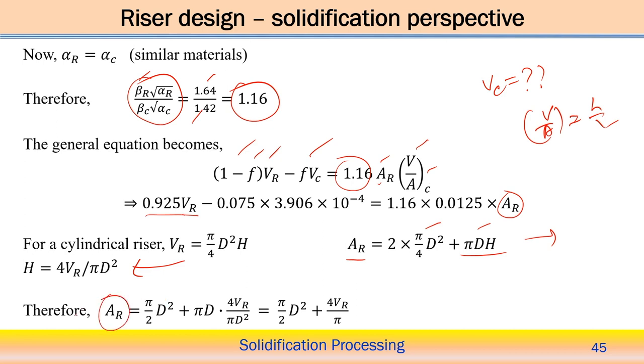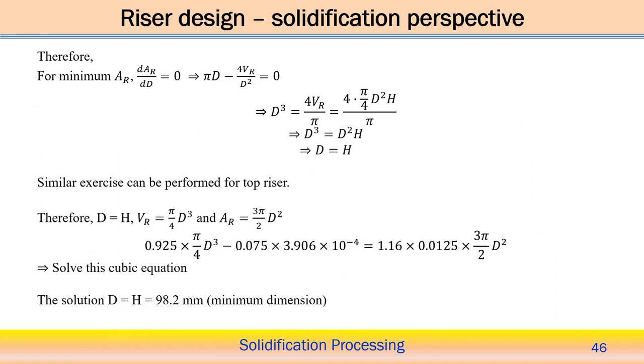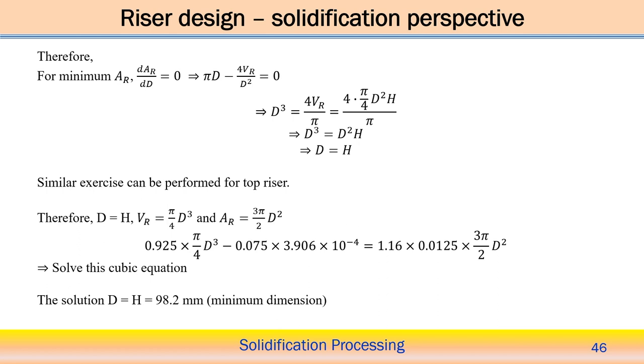Now Ar can be calculated like that: pi by 2 d square plus pi d h. We put the value of h in terms of the volume, so pi by 2 d square plus pi d into 4 Vr by pi d square. So this we are getting. Now we can find the dimension such that the heat loss from the surface of the riser will be the minimum, and heat loss from the riser depends on the surface area. That is why we calculate the minimum value of the surface area in this particular design of the riser. If we set dAr by dd equal to 0, we can get this expression.